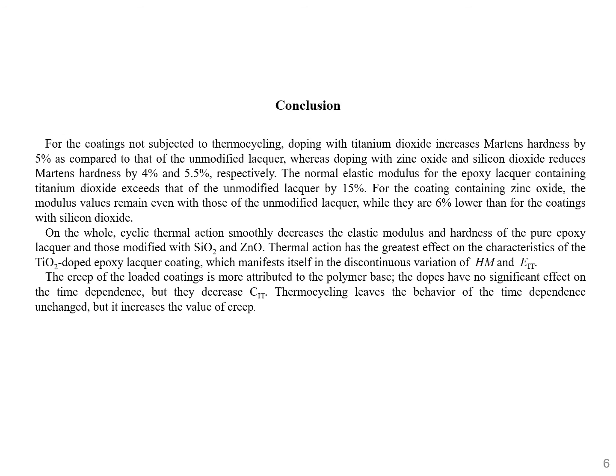On the whole, cyclic thermal action smoothly decreases the elastic modulus and hardness of the pure epoxy lacquer and those modified with silicon dioxide and zinc oxide. Thermal action has the greatest effect on the characteristics of the titanium dioxide doped epoxy lacquer coating, which manifests itself in the discontinuous variation of hardness and modulus. The creep of the loaded coatings is more attributed to the polymer base. The dopes have no significant effect on the time dependence, but they decrease modulus. Thermocycling leaves the behavior of the time dependence unchanged, but it increases the value of creep.